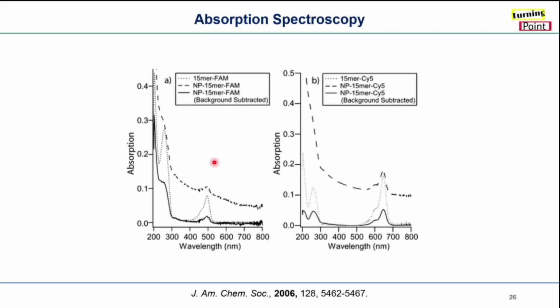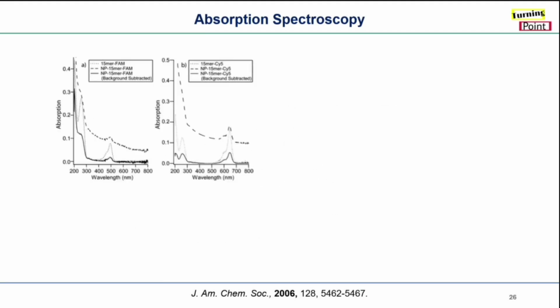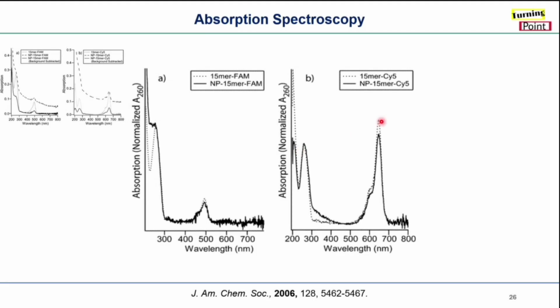Further, you can see the normalized absorption spectra. There is a small change in the observed spectra, which suggests a minor change is due to the radiative pathway. But the majority of these curves didn't change, which indicates it is a non-radiative pathway. If it were a radiative pathway, we would see a change in the absorption spectra due to the change in the oscillator strengths. And further, they extended these studies and investigated the size dependency of nanosurface energy transfer behavior.